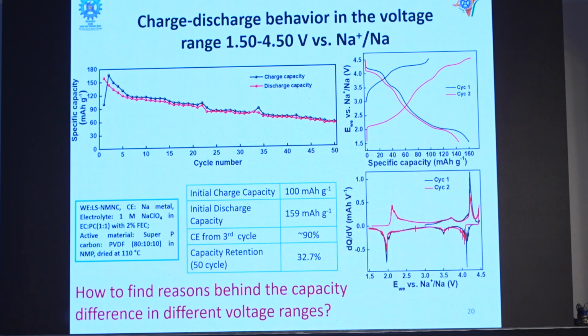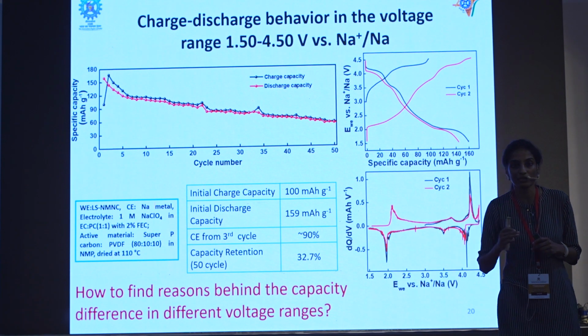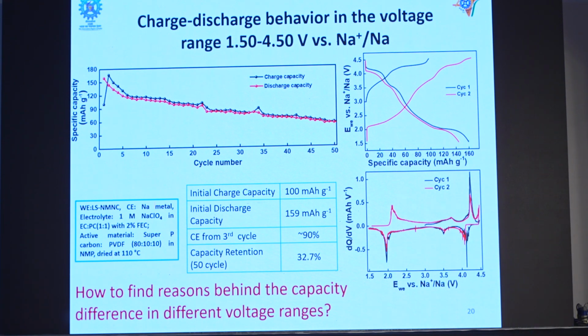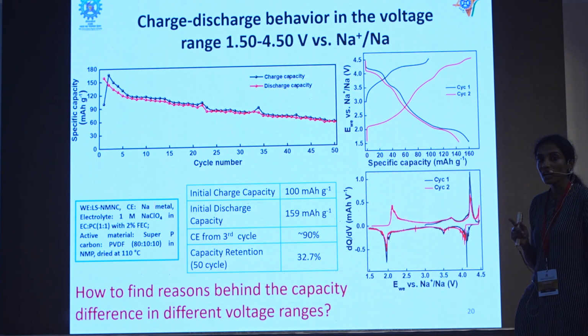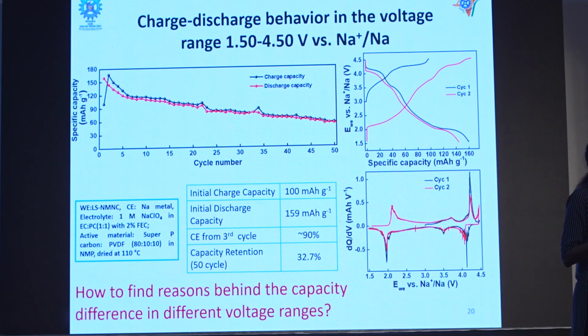And now what we have done, we have increased the upper cutoff voltage from 4 volt to 4.5. And why are we doing it? We wanted to see if we can activate any other electrochemical reactions in the system. So what are the other electrochemical reactions possible? We already talked about nickel, cobalt and manganese, and we have already seen the electrochemical activity of nickel, manganese and cobalt. But we have one more anion here, that is oxygen. And sometimes when you increase the upper cutoff voltage, you can actually activate the anionic activity, and the oxygen can undergo an oxidation reduction reaction with a metal, like oxygen is oxidizing and the metal is reducing. It's called a redox coupling mechanism.